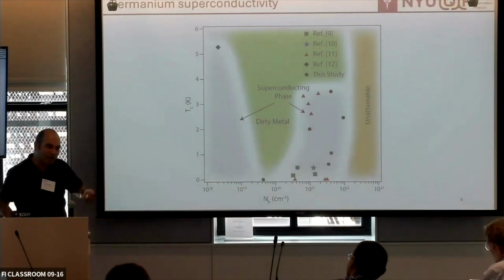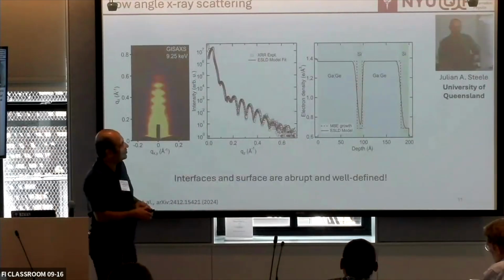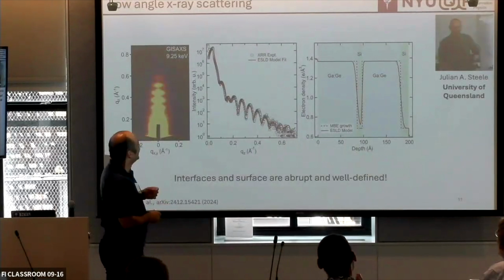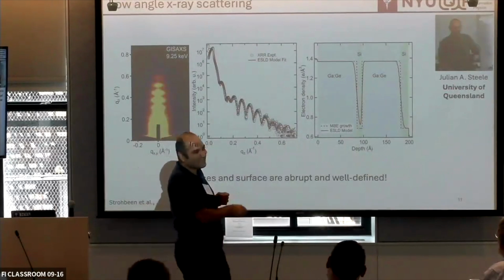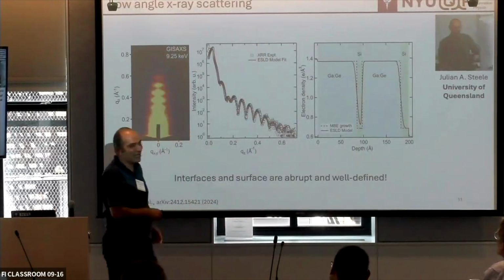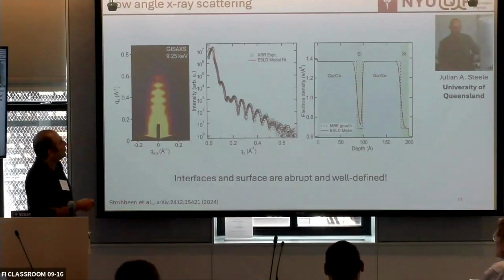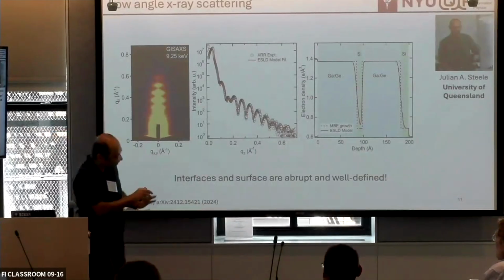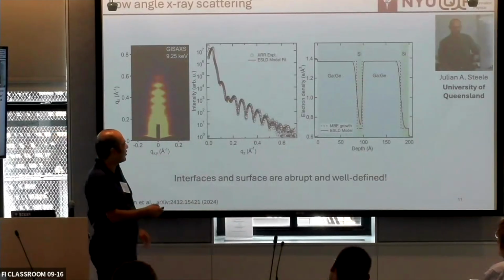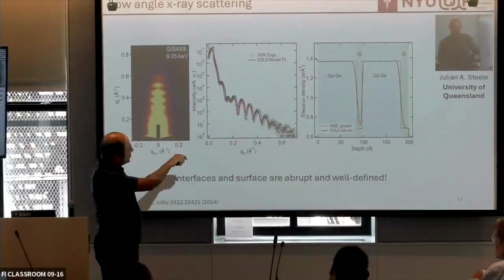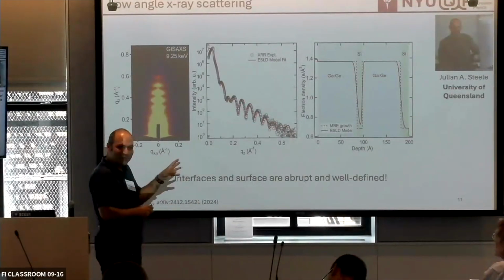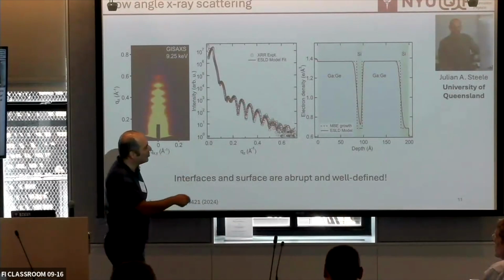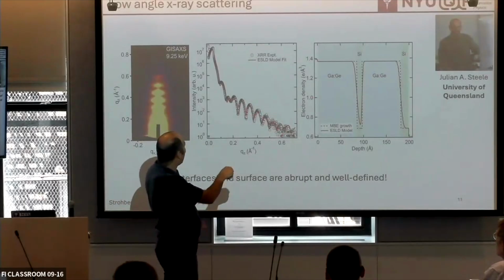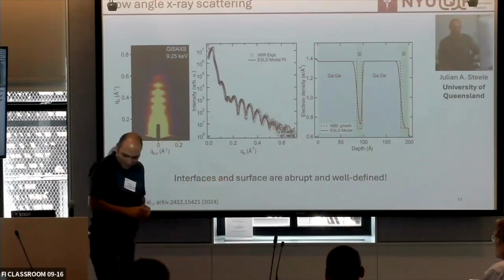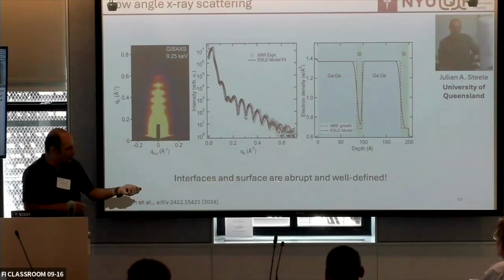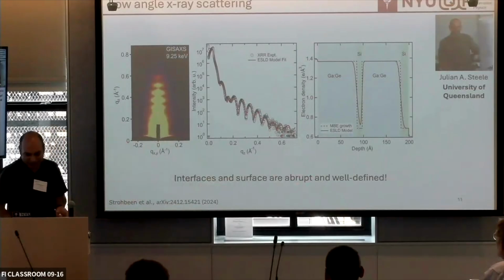But obviously, the moment you find this, everybody says, "Oh, are you sure it is the right thing?" And so we actually worked with the University of Queensland in Australia to do a lot of structural analysis, right? So we did very fine-tuned synchrotron-grade XRD to see these fringe patterns. We are only growing 5 to 10 nanometers, so you really need a high intensity beam, and it matches exactly the thickness that we grew. Very well-defined, abrupt, which was also confirmed with TEM separately.